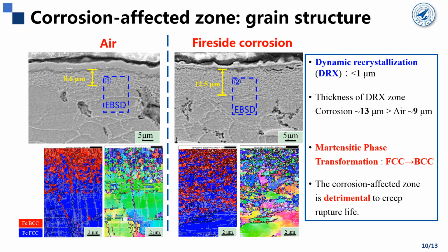Another important thing is that the mapping from EBSD scanning also proves the phase transformation from FCC structure to BCC martensite. And this is consistent with previous XRD results.